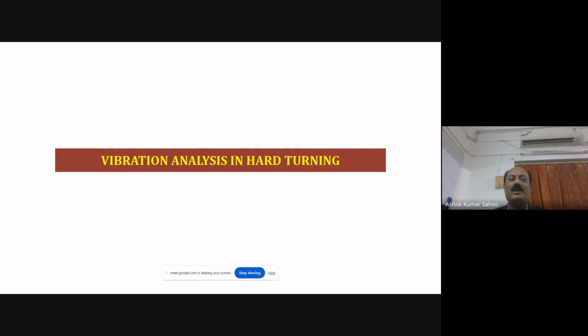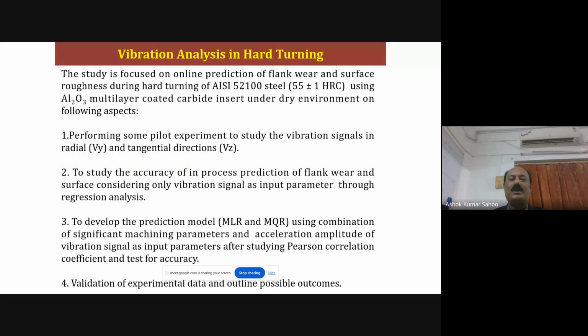So for the last case study, we focus on the vibration aspects and tool condition monitoring, considering vibration signal measurement to monitor the tool wear and surface roughness during the hard machining operation for smart machining, because vibration plays a very important role in the deterioration of surface quality and the growth of tool wear and tool life in hard machining, particularly where the radial thrust component force is higher as compared to the tangential force. That's why some pilot tests were conducted initially.